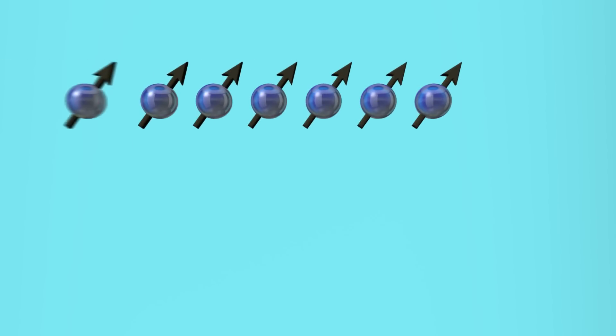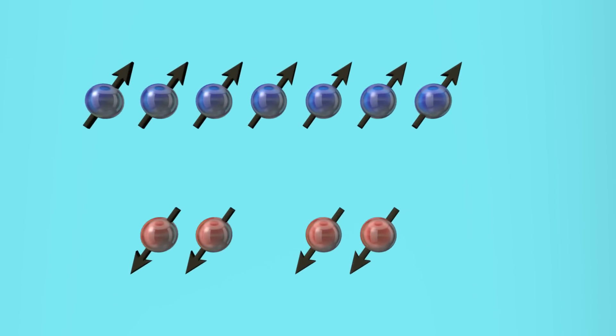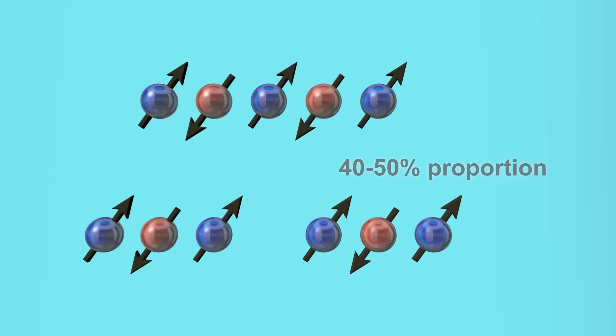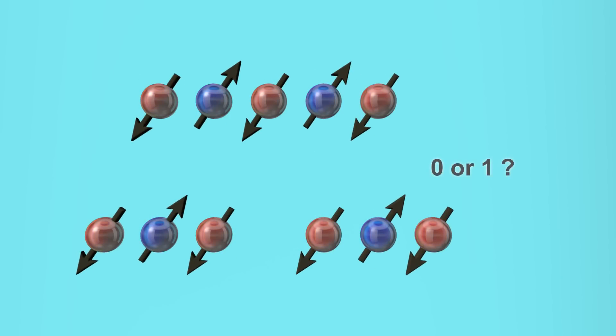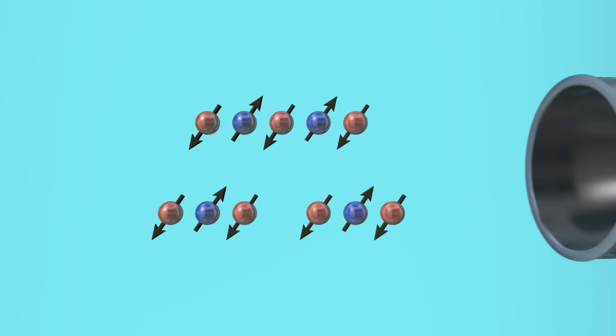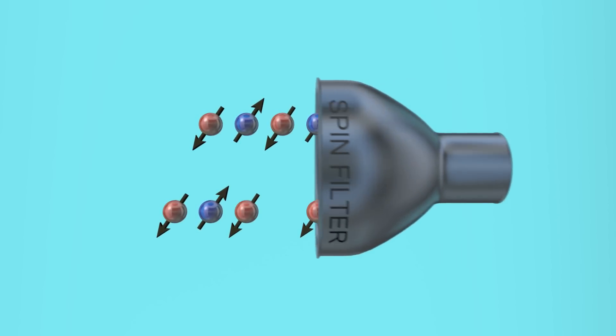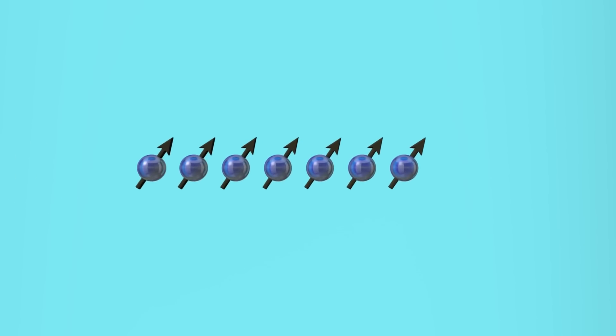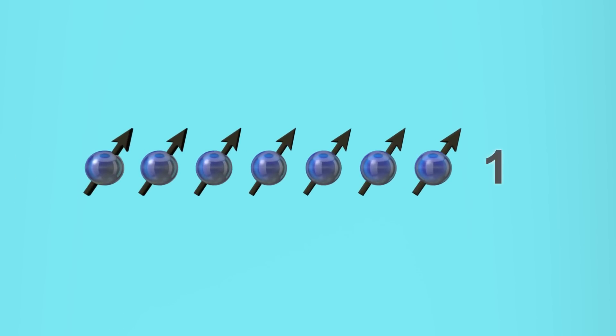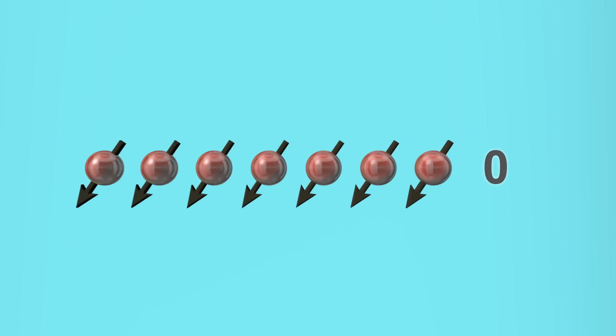But things are not that easy. Magnetic materials naturally have a fairly balanced proportion of spin-up and spin-down electrons, between 40 and 50%. This means that switching the orientation of the layers only marginally changes the electrical flow, so the resistance is never very high or very low, making it difficult to generate a 0 or a 1. To solve this, at NanoSelect we have created a filter that selects only either spin-up or spin-down electrons within the material. This way, we can increase the contrast between the two states of high and low resistance, so making small-sized memories more sensitive and easy to read.